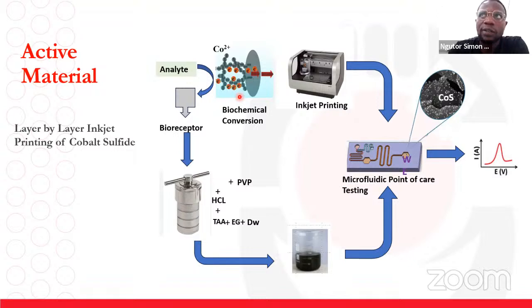Here, I did the synthesis where I used PVP, cobalt nitrate, HCl. This PVP here is a polymer, like I said earlier, some kind of binder. Or you could still call it an additive, because it helps to encapsulate the material, preventing it from growing in other phases. Then the HCl comes in here like a complexing agent. It also helps in dissolving the other undissolved particles, because since you're doing this at higher temperature, nanoparticles, because they are going to be in nano or micro range, have a tendency to agglomerate. So we need this PVP, and then thioacetamide is the sulfur source.